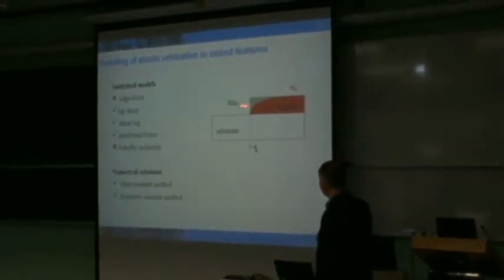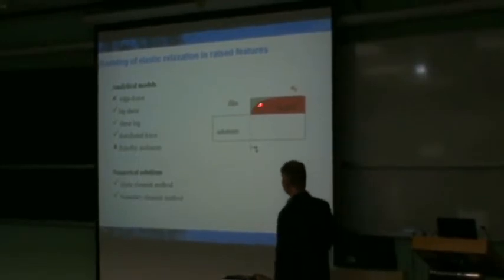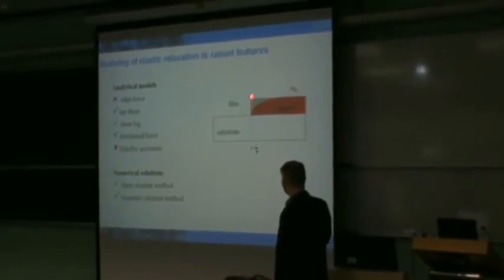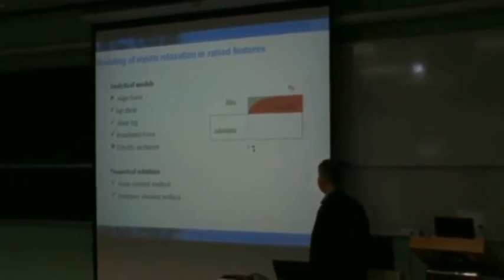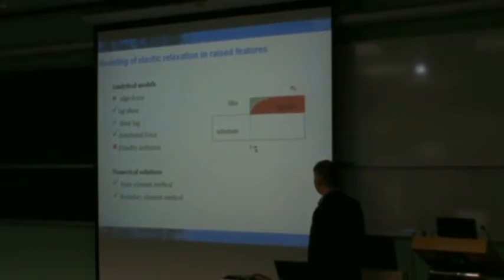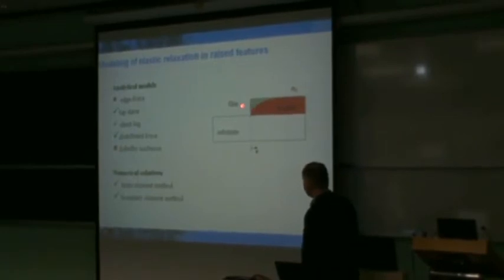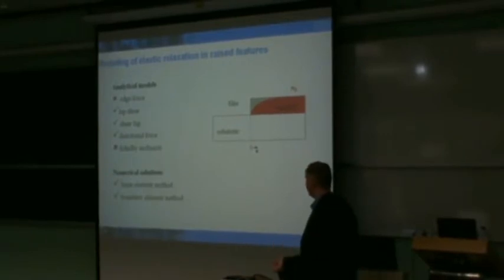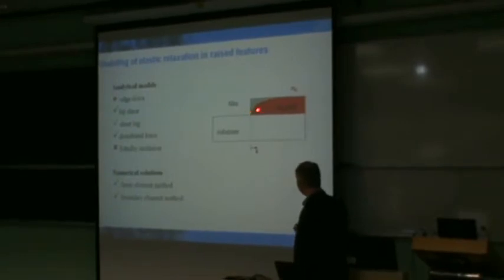What I'm showing here is the fact that the normal stress in this direction along x, say we have a film with an eigenstrain in it, and far away from the center, this edge in the film, that we have a certain far field stress that exists within the structure, and that sits on the substrate. And the fact that as we start to approach that edge, the amount of normal stress that is seen at this free edge has to be zero. This is just from Newton's second law, or Newton's third law, sorry. And so at some distance from that edge, you start to see the development of that stress.